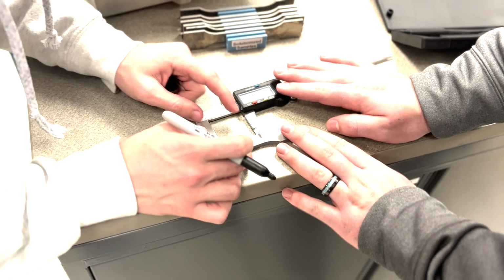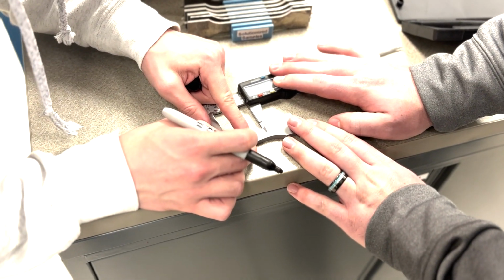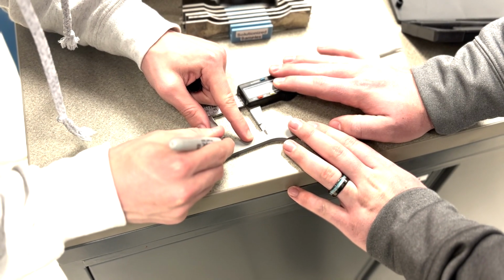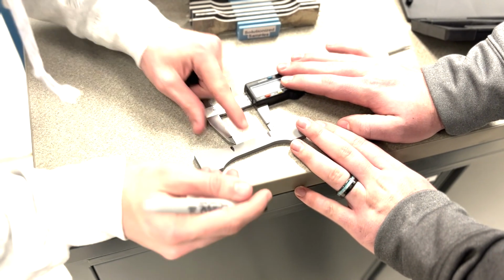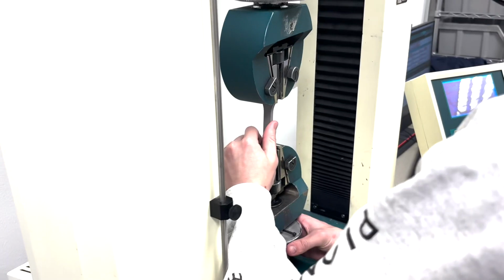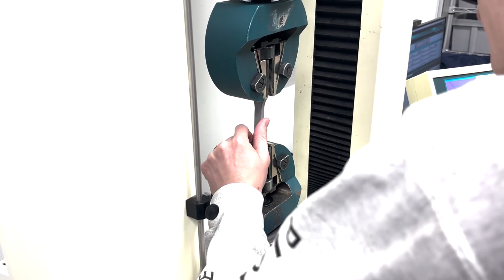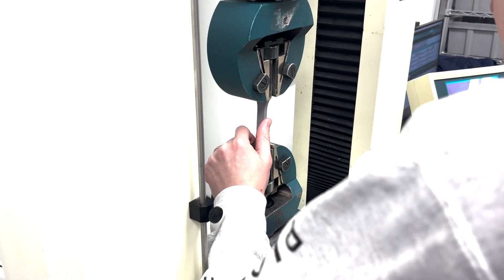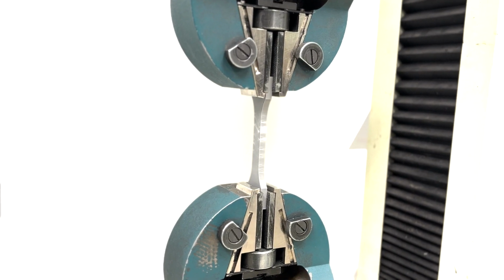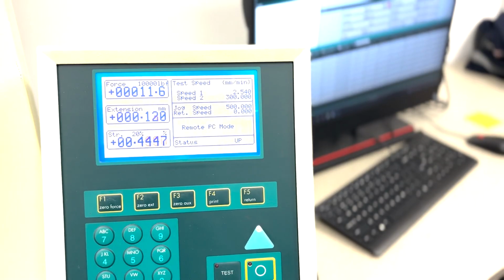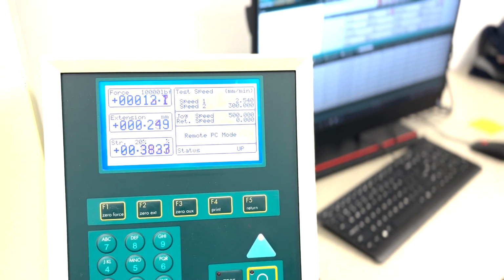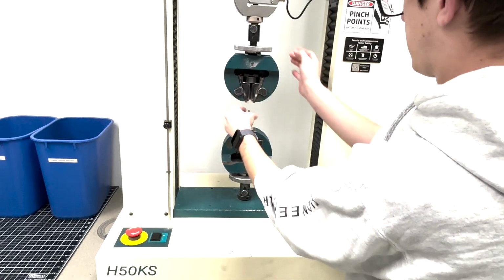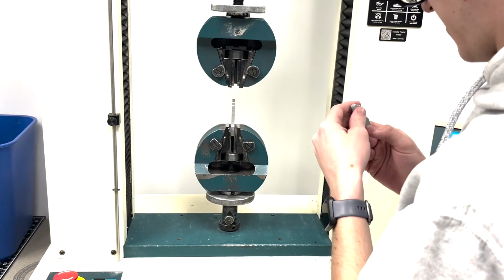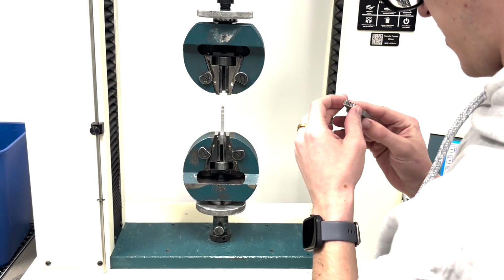A dog bone-shaped sample is 3D printed using PLA filament. The dimensions of the sample are then measured using a digital caliper with a resolution of 1/1000th of an inch. These dimensions are entered into the computer. The sample is loaded into the tensile testing machine, and the test commences. The load increases gradually until the sample splits. The data is recorded and saved for later use. The preliminary test worked perfectly, and is expected to be a robust system of measurement.